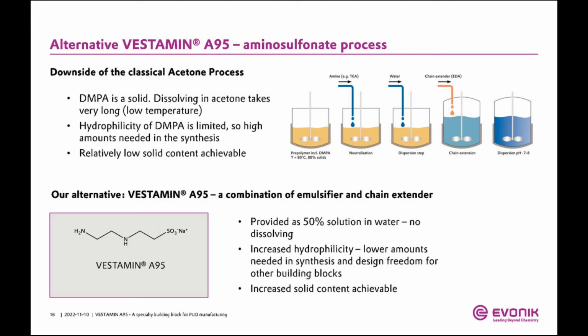So when we look at this process, it has some downsides on the handling of this whole synthesis process. First one to mention is the DMPA, our acid. Our emulsifier is a solid, and it's a hydrophilic solid. I mean, that's its role, right? So the dissolving in the acetone in the organic phase takes very long, and due to the fact that we use acetone, we have relatively low temperatures. We cannot heat it up to speed up the dissolving process. So here you often lose several hours in dissolving only the DMPA. Second is that the hydrophilicity of the DMPA is rather limited, so you need relatively high amounts to obtain the desired amount of hydrophilicity, so that you also get decent solid contents in your dispersion.